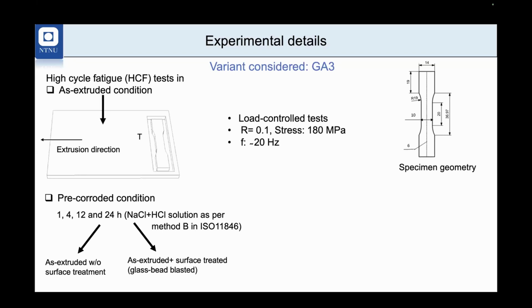Basically, we carried out a high cycle fatigue test, as you can see here. The specimens were extracted perpendicular to the extrusion direction. Additionally, we did some pre-corrosion, where we subjected the material to intergranular corrosion as per method B in ISO, for several different durations: 1 hour, 4 hours, 12 and 24 hours. We used two different conditions. One is as extruded without any surface treatment, and the second is as extruded followed by a surface treatment, that is glass bead blasted. For fatigue testing, we used an R ratio of 0.1 at a stress of 180 MPa, and you can see the specimen geometry here.